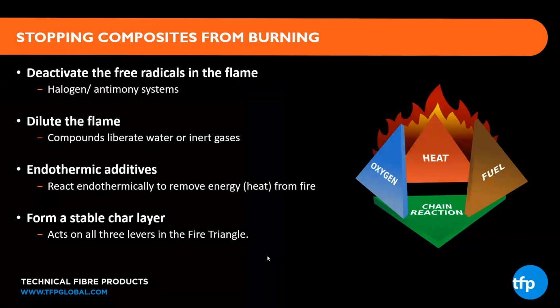And there's two real advantages in terms of the char layer approach. One is that it doesn't offer any of the disadvantages of the above strategy, so you're not generating more toxic fumes, there isn't a negative impact on weight or mechanical properties, and it actually acts on all three levers of the fire triangle. So that stable insulating char layer reduces the oxygen and heat from getting through to the backing laminate and reduces any fuel source that's liberated in a gaseous form from leaching out into the flame front and acting as a fuel source.